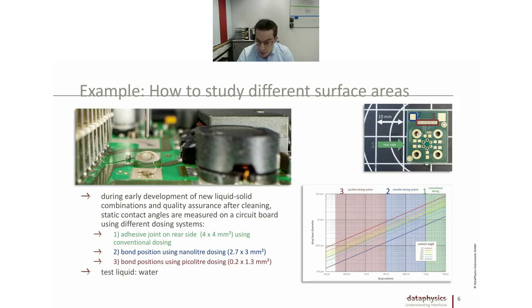And here in this table, you can judge a little bit how small your droplets need to be in order to conduct this measurement. We have divided it into 3 sizes: conventional dosing in the microliter range, nanoliter dosing, and picoliter dosing. And you can see, depending on the expected contact angle that you will get on this kind of surface, you have to choose the volume. So just imagine if you have a system that can dose 10 nanoliter, the expected contact angle is around 90 degrees, then you are good to measure on an available surface area that is probably only 200 micron wide. There the drop can fit in.